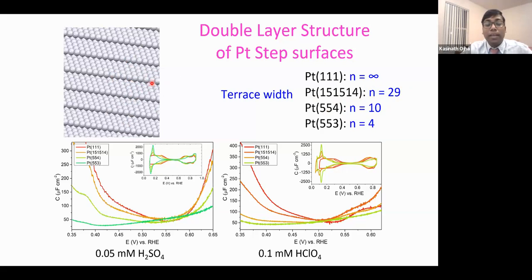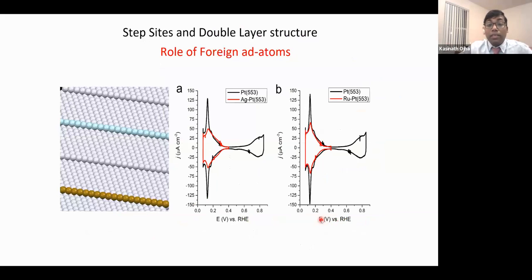And then look at the double layer capacitance. If you look at the capacitance value, this place is the potential of zero charge, where we look at the Gouy-Chapman capacitance. Here we don't change the capacitance much. It's almost the same, but the only thing is the minimum is shifting a bit towards lower potential. Same as here. These are two different electrolyte measurements, but they are basically the same. Now, what we did is we added foreign atoms, we deposited foreign atoms on these step sites.